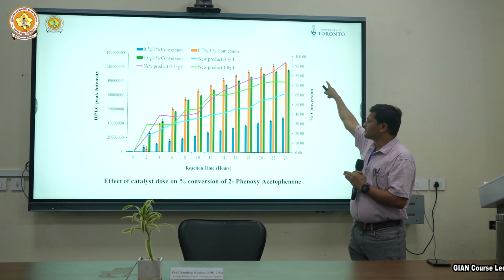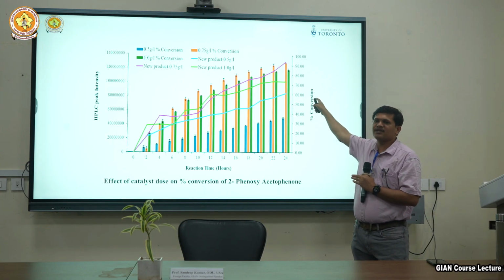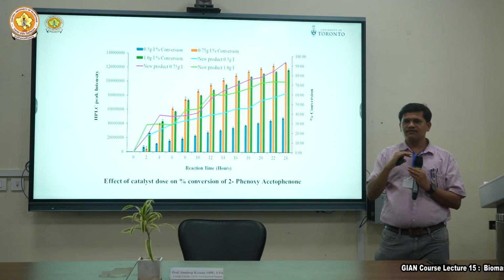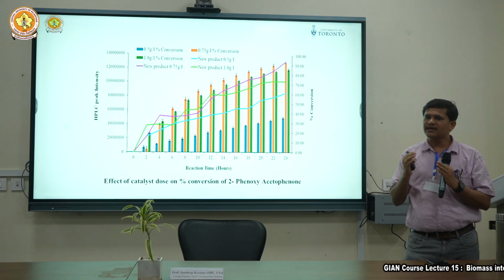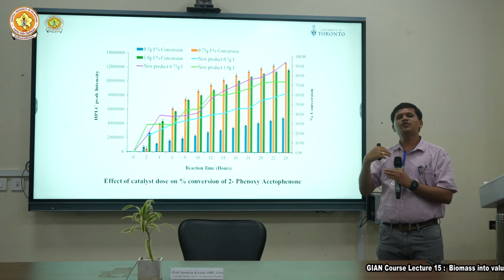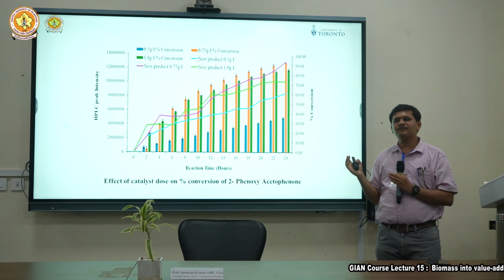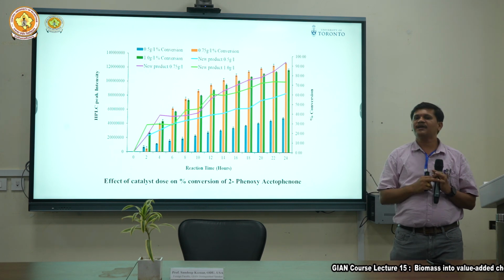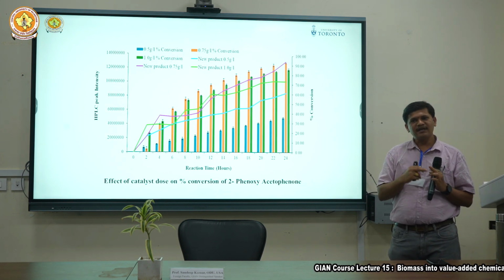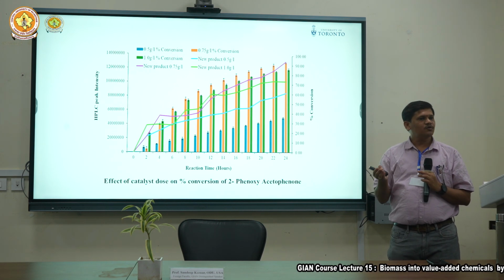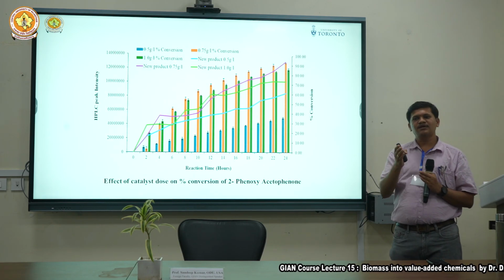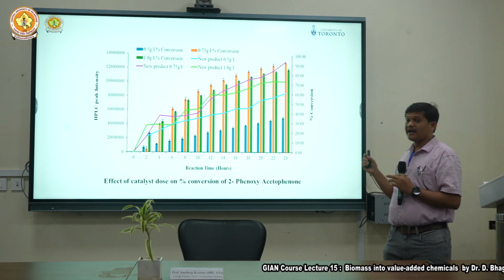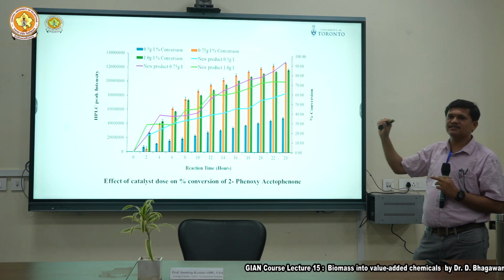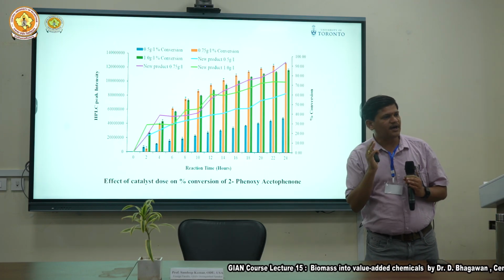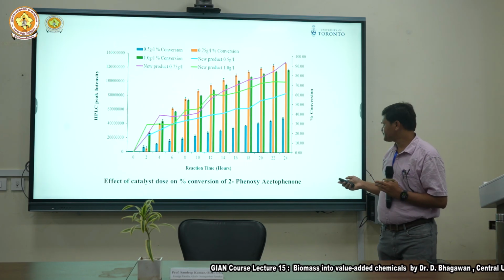But after that, the continuous conversion has been carried even up to 24 hours, with stable production. So the conversion of lignin into new product has continued up to 24 hours. Still there is no deactivation of catalyst, even without photo intensification it is working towards the depolymerization of lignin at selective sites. The beauty of this research is that it cuts the compound at selective sites.